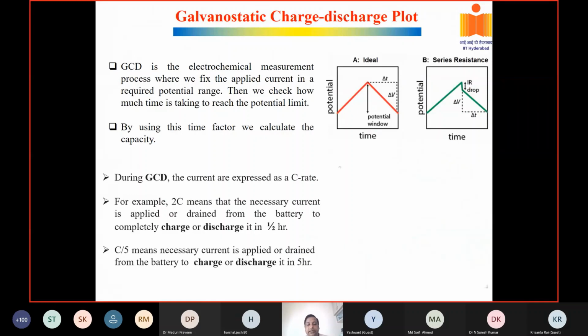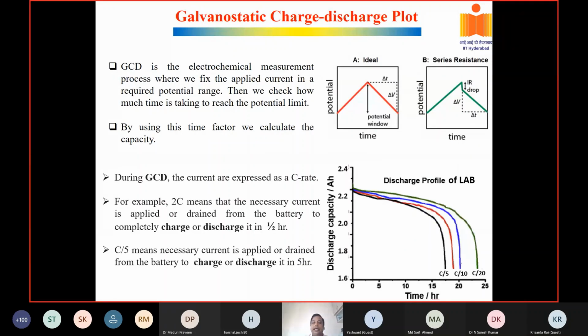We also do charge discharge. Another important thing is charge discharge. This is very, very important. It gives you the voltage profile when you discharge at different C rates. As I told you, 1C refers to the capacity in 1 hour. C by 10 is the 10-hour charge discharge, C by 5 is the 5-hour, and C by 20 is the 20-hour charge discharge. See the voltage profile. If you are getting 25 hours, this is the C by 25 rate.